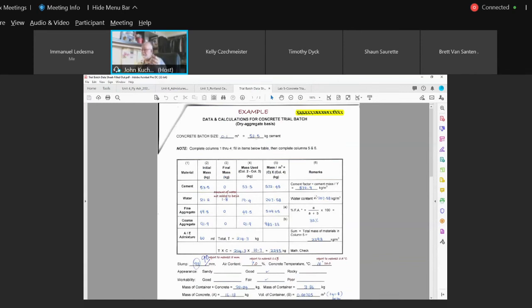We need 541 kgs per cubic meter of cement for our mix design. If it worked out that we ended up having 540 or 539, which is minimal, the client might say, hey, you're shortchanging me. The spec says, your mix design says, a minimum of 541. You only gave me 540. I want a credit on the mix or whatever. See what I'm getting at?